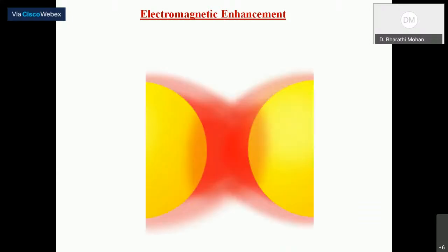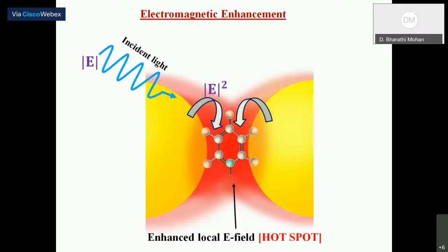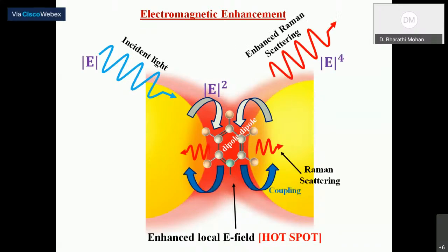So what is electromagnetic enhancement? If a molecule is placed near a dimer, when light is incident, it excites a surface plasmon resonance, which increases the localized electric field. This localized electric field excites the Raman scattering of the probe molecules, which then again couples with the localized electric field and increases the Raman scattering to the level of E to the power 4. This way, by localizing the electric field between the nanoparticles, one can increase the Raman scattering of the probe molecules.